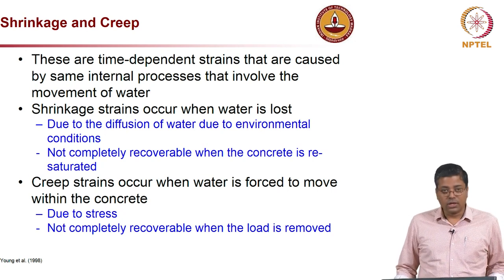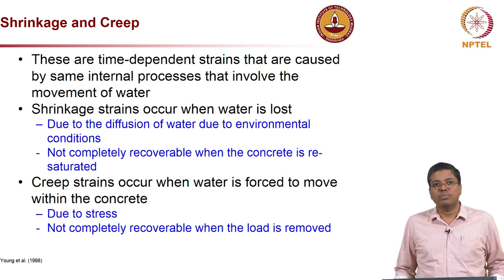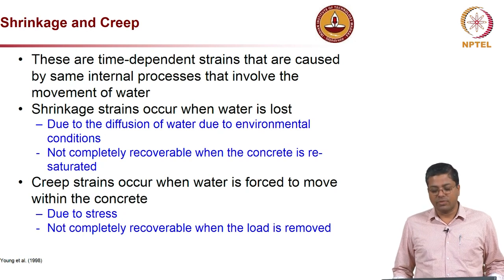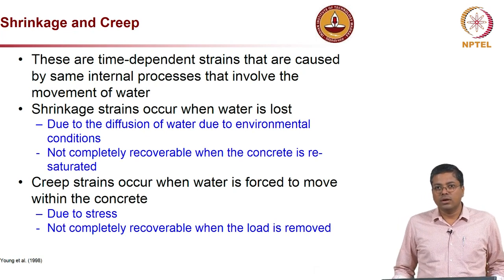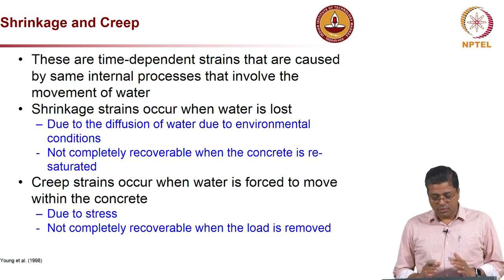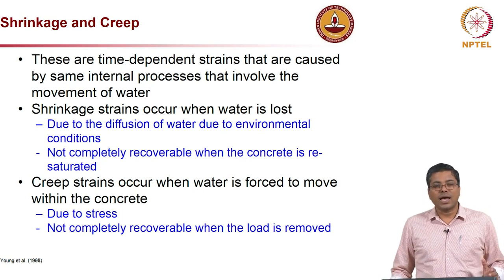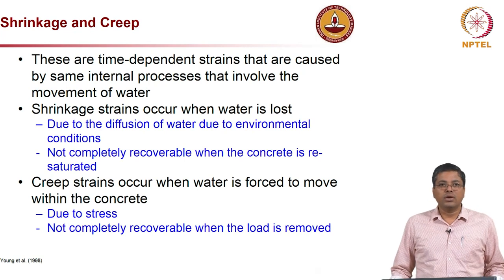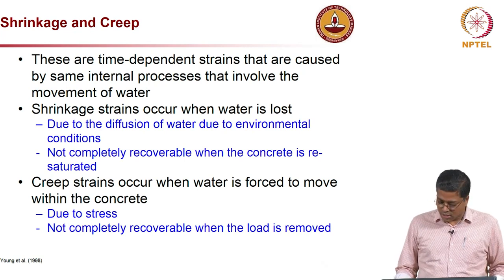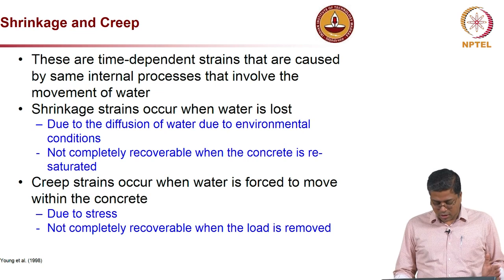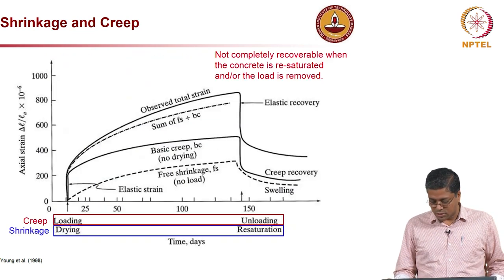And one thing to note here is that both the creep strain and the shrinkage strain are not fully recoverable when the load is removed or when the concrete is resaturated, respectively. Once the creep and shrinkage happens, it is very difficult to recover the strain which is caused.